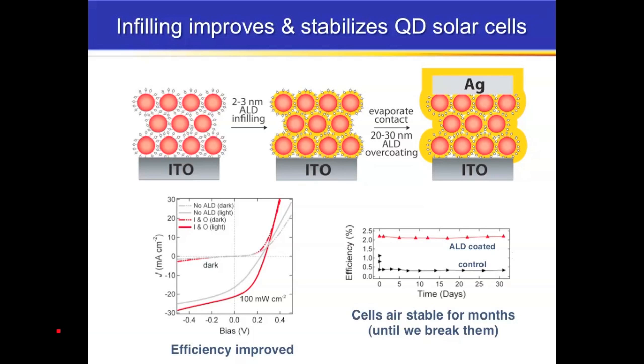And so we can apply this technique also to solar cells. We have to do it a little bit differently than what we would use for field effect transistors. We usually use a two-step process for solar cells. We would take a conductive film. In this case, the film is selected to be a pretty low performance material and also to be very air unstable by design. We do a first step of ALD infilling, just a very thin 2 to 3 nanometer ALD infill that allows us to just alter the conduction properties of the material. We then deposit a top contact, in this case silver. The silver punches right through this very thin alumina layer to make contact with the quantum dots. And then we do a second ALD overcoating step that allows us to get air stability. This one's a thicker ALD coat.